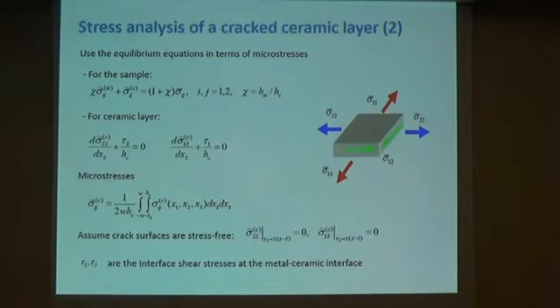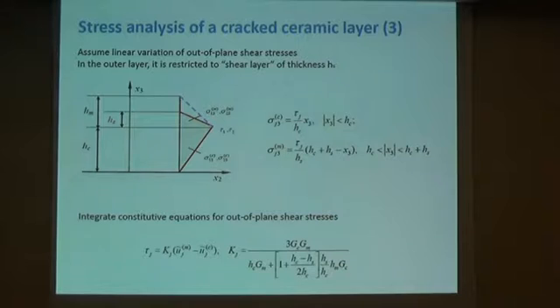So this is how we perform stress analysis of the sample. We average stresses across the thickness of the layer and width of the sample and produce these tilde stresses. And we have equilibrium equations for ceramic layer and for the whole sample. In terms of these microstresses, we assume that crack surfaces are stress-free. And when we write our equations in terms of microstresses, we end up with tau1, tau2 interface shear stresses at the metal-ceramic interface.